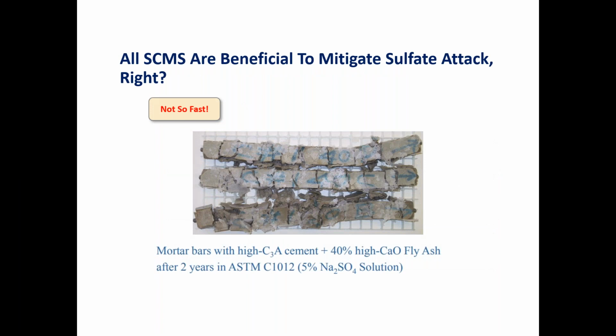So here's an example of a situation where adding SCMs is actually detrimental. In certain areas of the country, there are a lot of Class C fly ashes. And I don't want to say Class C fly ash is bad, but I want to say that it doesn't necessarily solve durability problems, and specifically with regard to sulfate attack. There is an established breaking point, and it all has to do with the calcium oxide. As you move from Class F fly ashes, which can have calcium oxide contents of 2 and 3% and higher, you move into that 18% threshold. You're getting into Class C fly ashes, and they have less pozzolanic reaction and more cementitious or cementing reaction. So Class C fly ash will actually react.